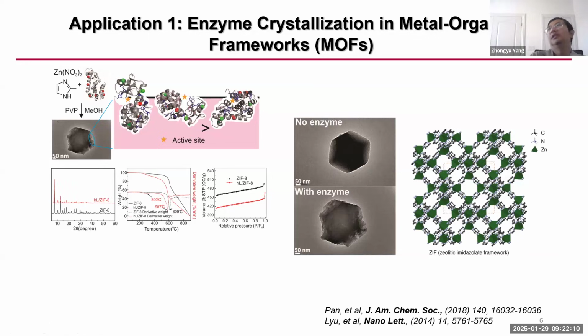So our hypothesis is that these enzymes are partially trapped, partially protected, but also partially exposed. And therefore, you can do activity tests, especially when the substrate of this enzyme is huge. We're talking about a micrometer substrate which cannot diffuse into the pores of the MOF. So exposure of the active site of the enzyme above the MOF surface becomes important.